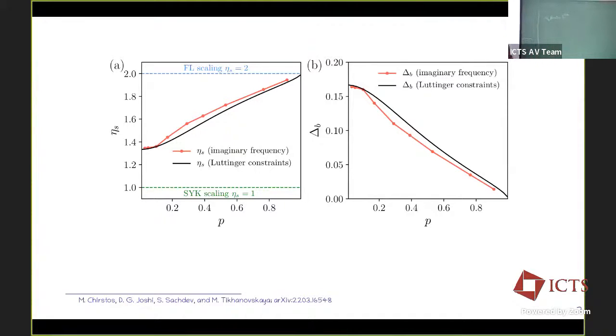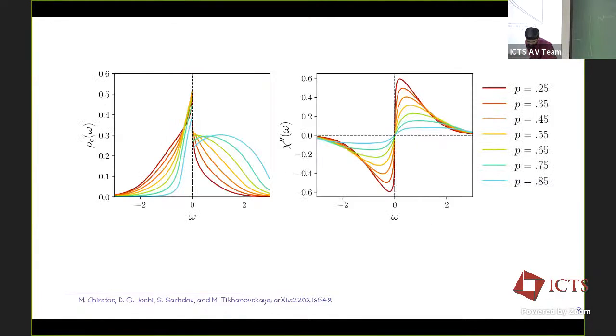Okay, so this is what I'm showing here, that the main thing is that the spin critical exponent now varies with the doping. And just to show you, we can also calculate the zero temperature spectral function. On the left is the electron spectral function. On the right is the imaginary part of the spin correlator. And as you can see, there are a set of curves for different dopings, and it's color coded here.